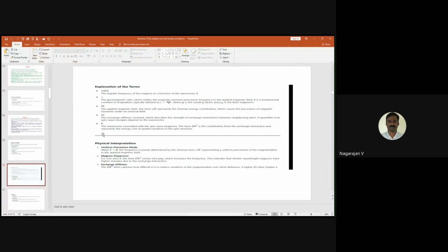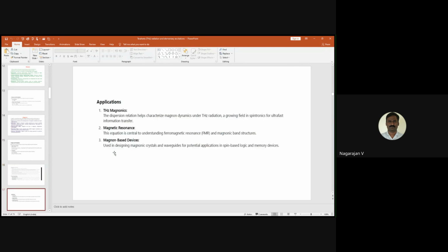On magnon dispersion, suppose k equals non-zero, the term D k square comes into play, which increases the frequency. This indicates that shorter wavelength magnons have higher energies due to the exchange interactions. The D k square term captures how difficult it is to induce variation in the magnetization over short distances. A higher D value implies a stiffer spin system. So this dispersion indicates that shorter wavelength magnons have higher energy due to the exchange interactions. So this dispersion is giving that many applications.